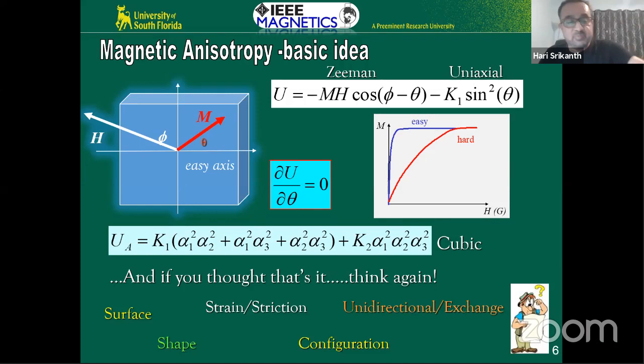In fact, nanoparticles are all about surfaces, right? Anybody that is working in nanomaterials of any kind, you're a surface scientist, because what you're doing is basically the surface atoms are being controlled, and the surface atoms play the most important role in determining the physical properties of the material, whether it's magnetic or whether it's semiconducting, it's the surface that matters. So that's one way to change the anisotropy, by changing the surface structure or the way in which the atoms are arranged. Shape is quite obvious, because if you give a preferred shape, for example, if you take a nanowire or a nanotube, the longitudinal axis is the preferred direction. So it's easy to magnetize it along the longitudinal axis. So in that sense, shape anisotropy is very obvious, that you can actually change the anisotropy and the nature or the shape of the magnetization curve.